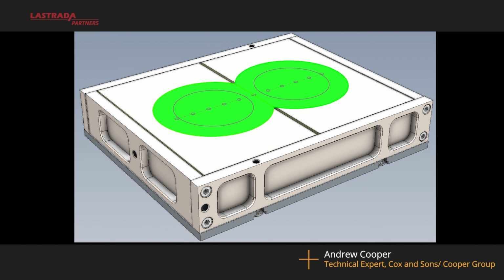The reason I've drawn the 100mm circle within the 150mm circle is that if these were dynamic modulus pucks, you would extract the central portion of the puck with a core drill, because people know that the outside is where you have poor voids because of the boundary conditions or the boundary effect of the mold. So it's a very poor place to actually be taking those measurements.